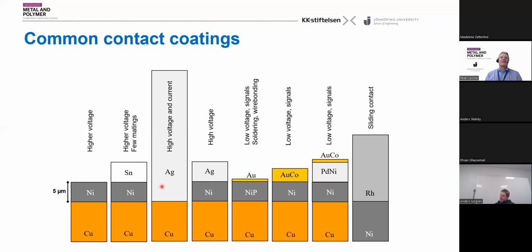We have the high voltage contact with silver. There you demand 20 micrometers of silver if it's a thick coating for high quality contacts. If you want a little lower quality contact, you can have an intermediate nickel layer and reduce the thickness of the silver. Then we have for electronics or electronic signals also copper, nickel or nickel alloy and gold on top. This is, for example, what you will have on your smart card if it's golden. If it's not golden, then it's because you have palladium on top.